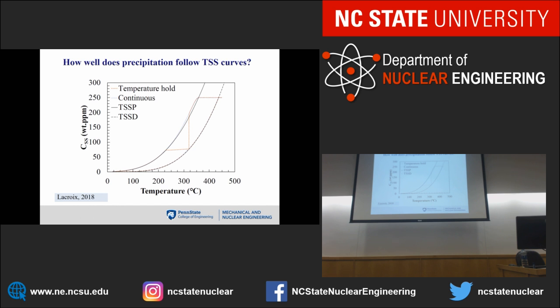Now, my student imagined, okay, what would happen if I stop here? I shouldn't get any more nucleation because I have already precipitated what I had, but what might occur is that the hydrides might precipitate by growth, not by more nucleation. And this is what would happen here. I would go all the way down to here. If he's correct, that means that this limit here is just a kinetic limit, and if I wait long enough, I get down to the solution temperature. So here's his data. So this is nucleation, and this is growth.